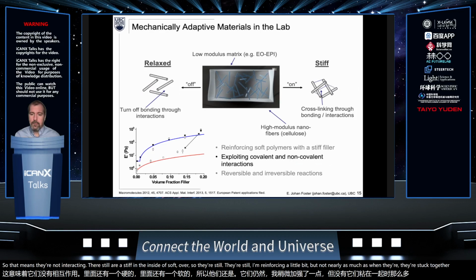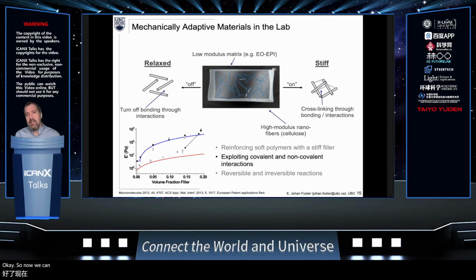Okay. So now we can create a material that, when it is dry, those cellulose nanocrystals are stuck together, and when it's wet, it becomes much, much softer. So order of magnitude change in the stiffness of this material. And it is very reversible. Again, not very quickly. It is controlled by the diffusion of water into the system, and then the drying of the water out of the system to couple and decouple those interactions.